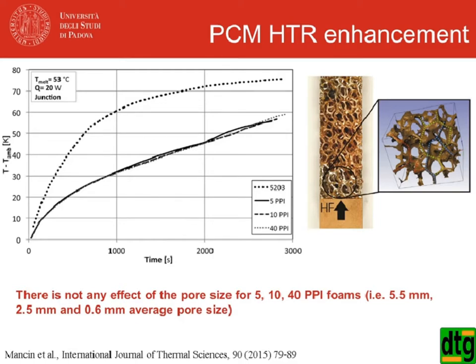So the junction temperature is reduced, which means that the heat flux that was supplied was conveyed inside the PCM rather than just in the liquid just melted. In fact, the liquid was extremely hot, extremely superheated, okay? Because the PCM basically is an insulator. It is not a heat transfer medium. So when the melting process started in the PCM without any enhanced surface, what happened is that just a small part of the PCM in contact with the hot surface started to melt, and then proceeded very slowly up.